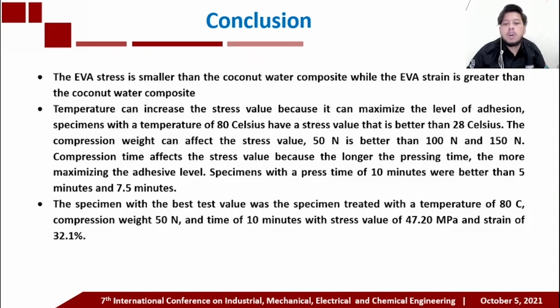The EVA stress is smaller than coconut water composite, while the EVA strain is greater than coconut water composite. Temperature can increase the stress value because it can maximize the level of adhesion. Specimen with temperature 80 Celsius has a stress value that is better than 28 Celsius. The compression weight can affect the stress value. 50 Newton is better than 100 Newton and 150 Newton. Compression time affects the stress value because the longer the pressing time, the more the adhesive level is maximized. Specimen with pressure time 10 minutes is better than 5 minutes and 7.5 minutes.